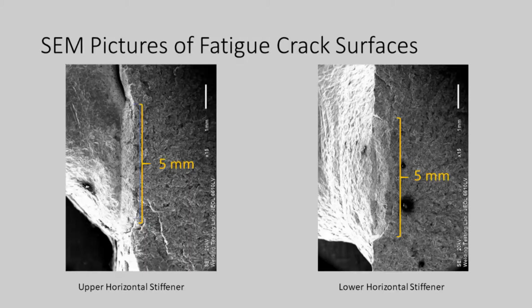Got in and did a little scanning electron microscopy. This is only at, I think, 15 magnification. And what do we see? Well, we see something pretty much similar, and somewhat similar to the last bridge in a way. We see this artifact here and this one here, and they're roughly the same size. They're not big. They're about 5 millimeters again, and maybe a millimeter deep.